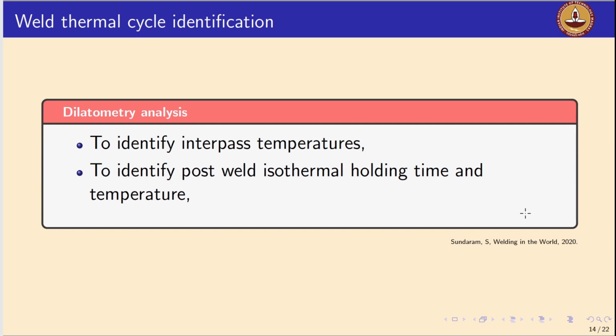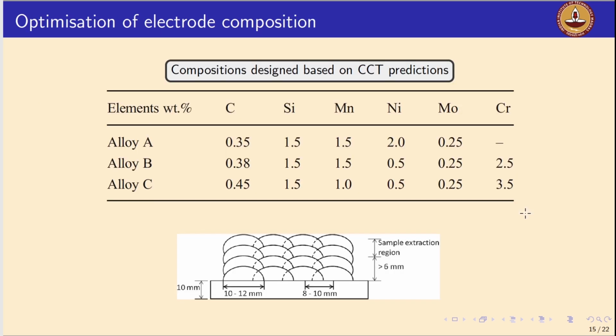So how do we identify these temperatures? I showed you in the earlier graphs, the CFB microstructure is stabilized by using an isothermal holding. So once we optimize the chemistries, we take samples from all welds and carry out extensive dilatometry analysis. The purpose of dilatometry analysis is to identify the interpass temperatures and the post-weld isothermal holding time and temperature.